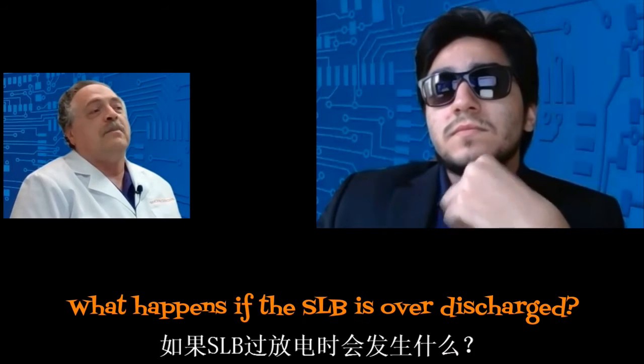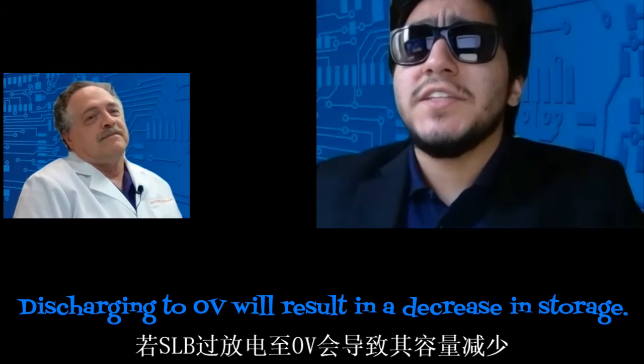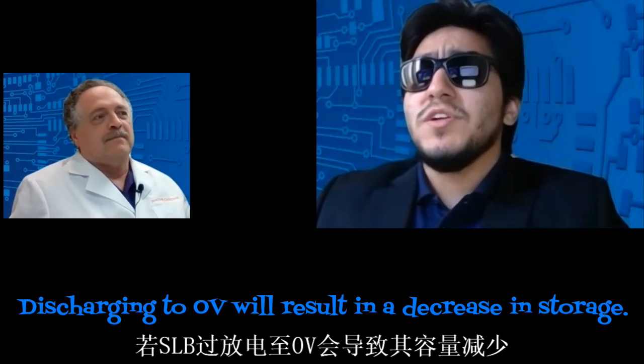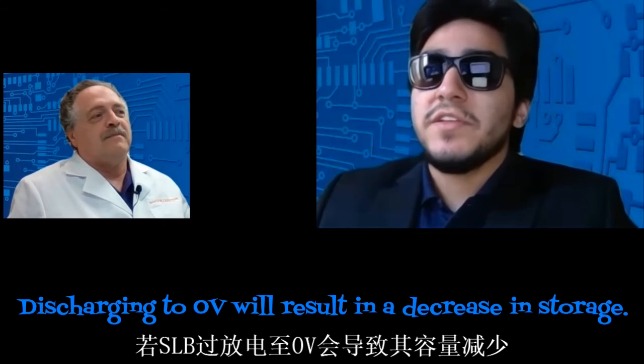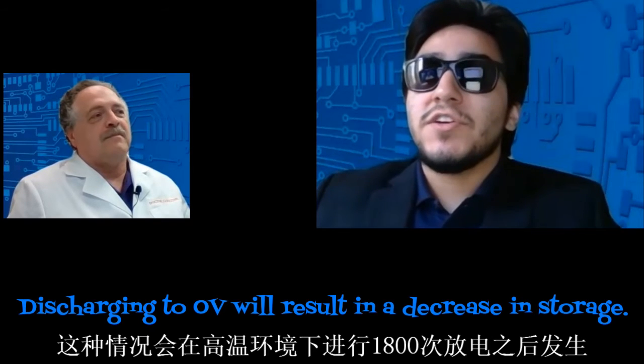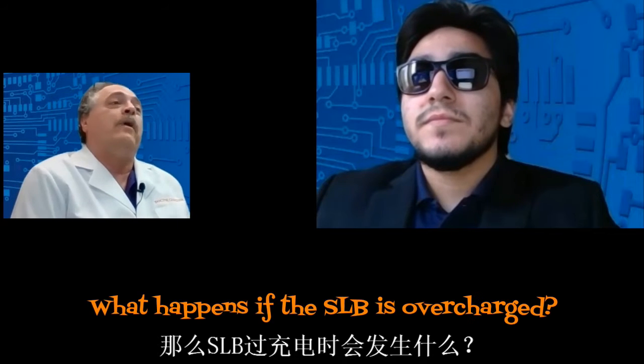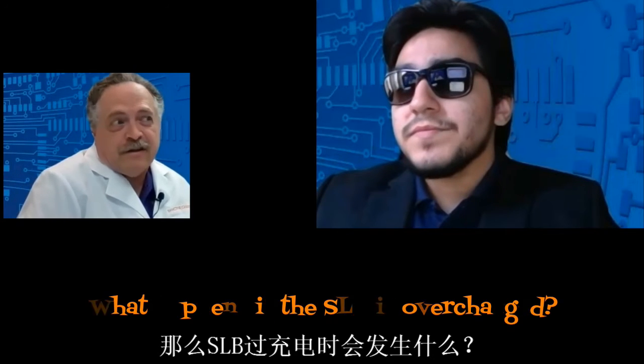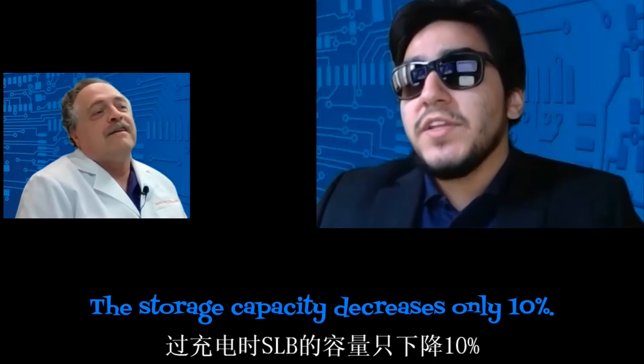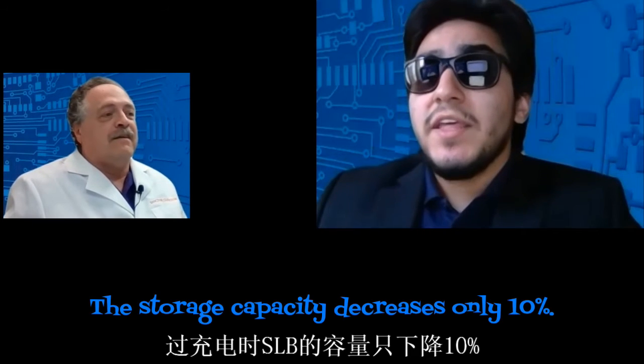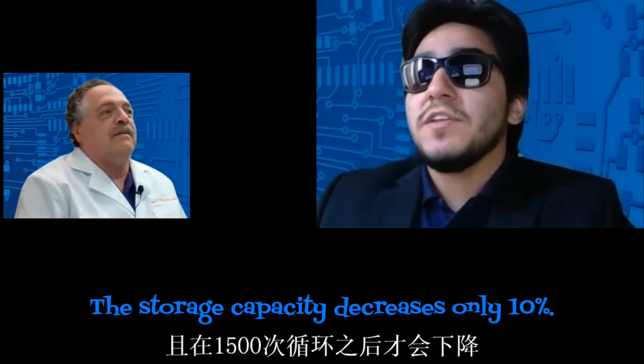What happens to the SLB if I over-discharge? Excess discharging the SLB down to 0 volts will result in a decrease in the storage capacity after 1,800 discharges at elevated temperatures. Okay, then. What happens if the SLB is overcharged? Well, the storage capacity decreases by only 10%, and it will take about 1,500 cycles to do that.